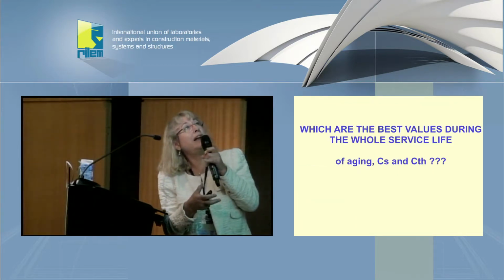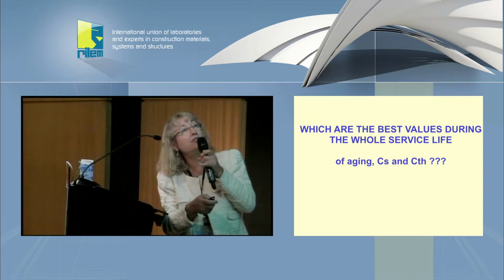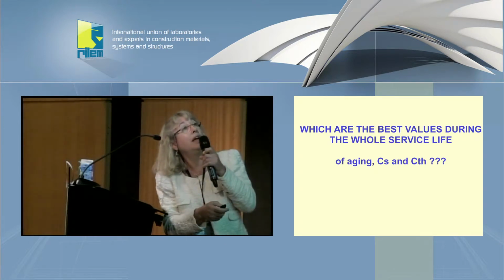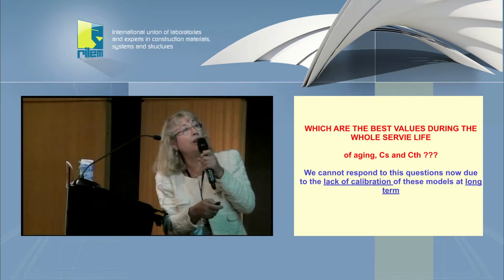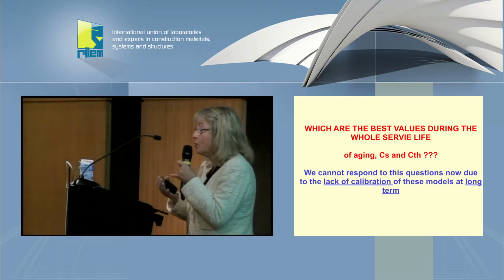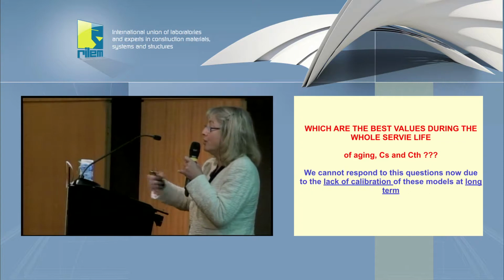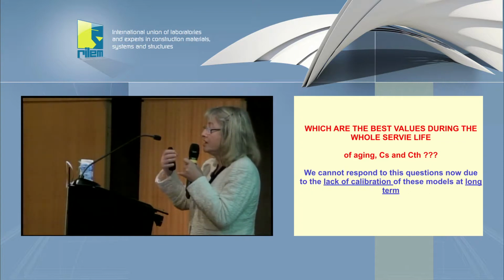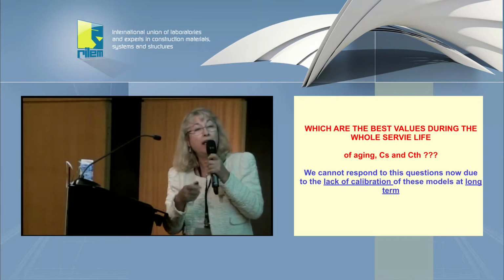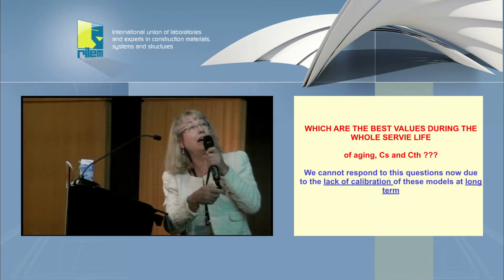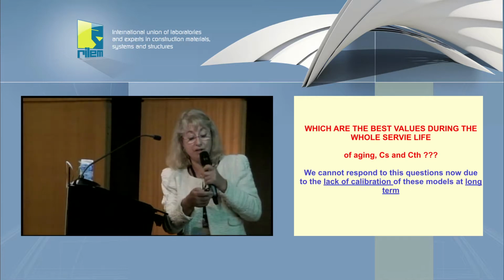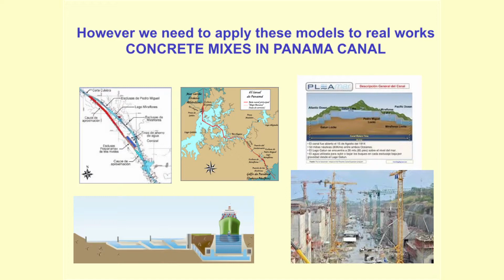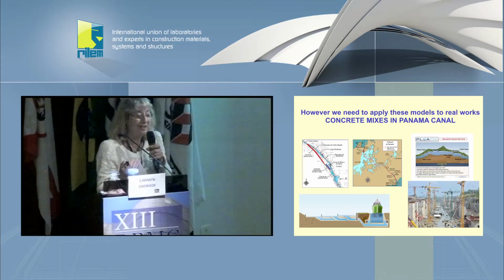Which are then the best values during the whole working life of aging, surface concentration and chloride threshold? Really, we cannot respond to this question now due to the lack of calibration of these models at long term. And this is what we need to assume. We don't have more record than 20, 30 years of following specimens and following structures, mainly for the aging, how they have evolved in the diffusion coefficient. However, we need to apply what we have now in real works, and this is the typical challenge of the engineers. We need to give an answer. We cannot wait 20 years to give an answer.